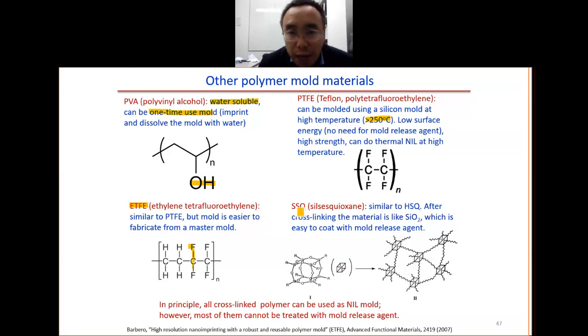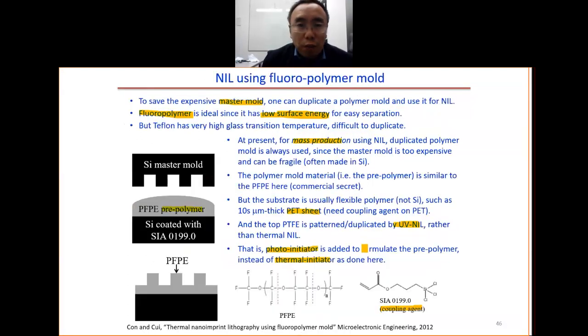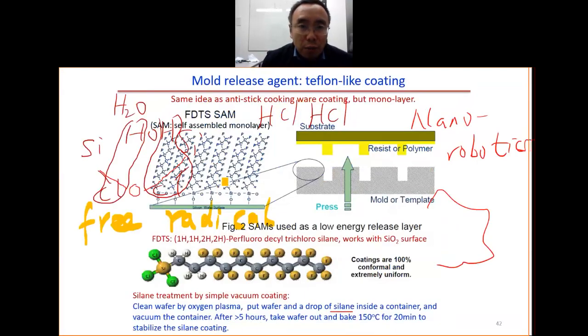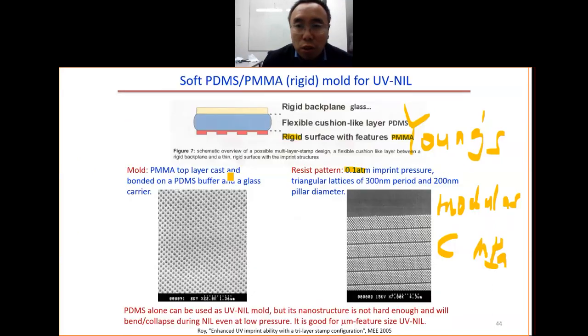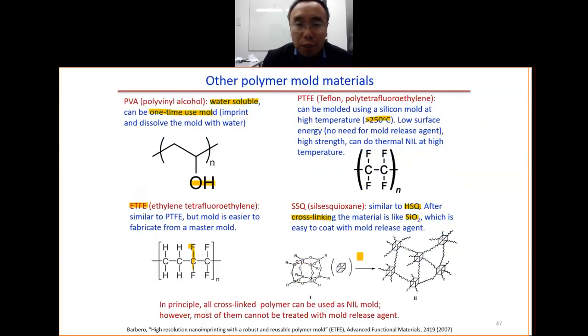The last example is the HSQ, hydrogen silsesquioxane. We know this one is the resist for electron beam lithography and also for X-ray lithography. Here it is similar, but we use it as the UV imprint resist. After cross-linking, this material is like silicon oxide. So if it is like silicon oxide, it is good for this process. It is good to make the surface a low surface energy for many-time imprint.